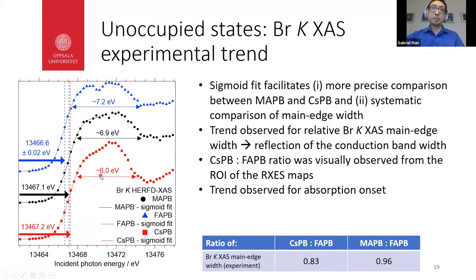There appears to be a trend where the width is narrowest for cesium lead bromide, increases for methylammonium lead bromide, and is finally largest for formamidinium lead bromide. In this table I've taken ratios relative to formamidinium lead bromide. There's also a systematic trend, because formamidinium lead bromide has the largest cation, so the absorption onset is lower relative to the two. Methylammonium lead bromide, the one in black, is in between, slightly smaller than formamidinium lead bromide. And cesium lead bromide is 83% of the size of formamidinium lead bromide. We'll explore this trend later.